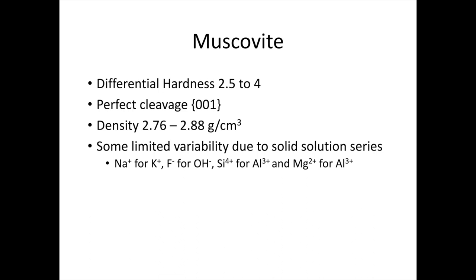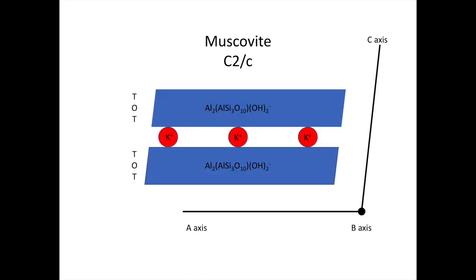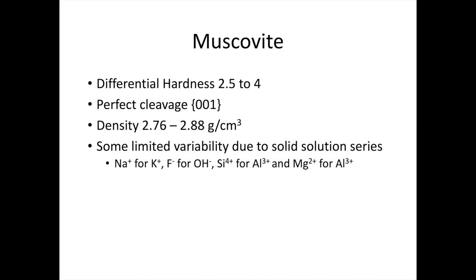The perfect cleavage of our muscovite along planes that only cut the C crystallographic axis of our muscovite is also a result of the sheet silicate structure of our mineral. The bonding between our potassium interlayer cation and those TOT sheets is weaker than the rest of the bonding in the muscovite structure. As such, when we pull apart mica sheets along this cleavage plane, what we're doing is breaking apart those potassium to TOT sheet bonds. Potassium, you are the weakest link. Goodbye. Whether it's the differential hardness or the perfect cleavage in the muscovite structure, hopefully it makes sense that the sheet silicate structure of our muscovite is causing a great deal of anisotropy with its properties.